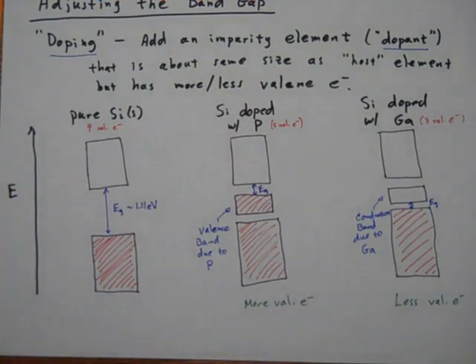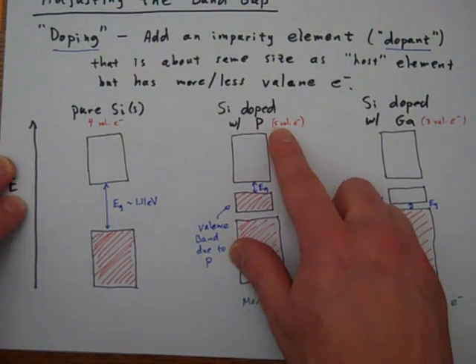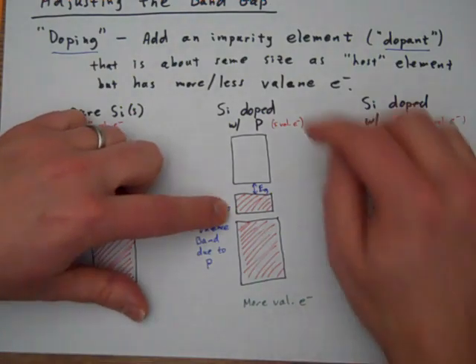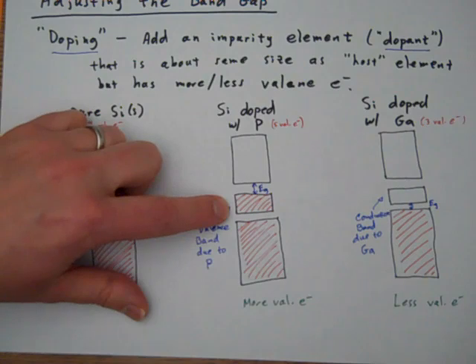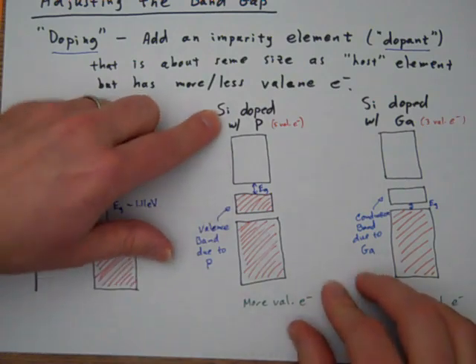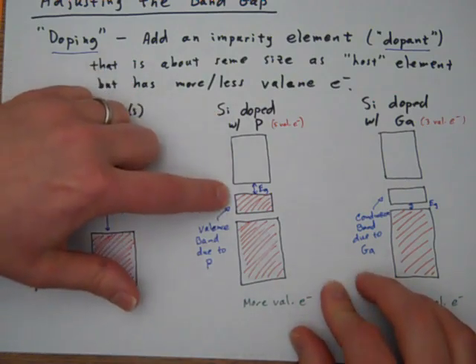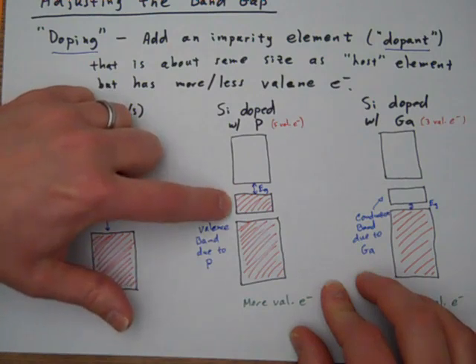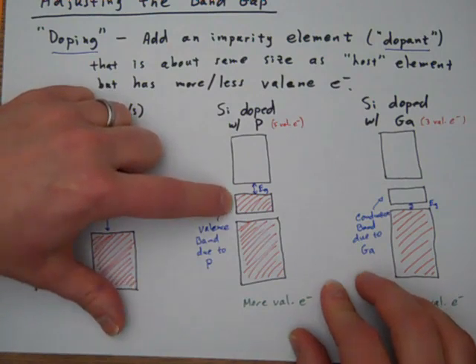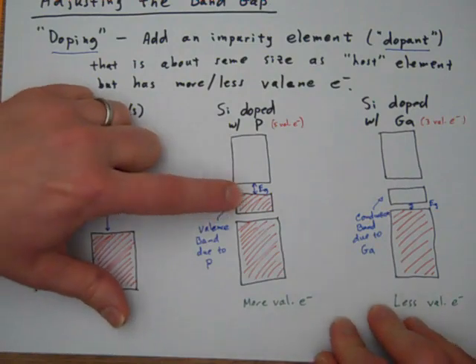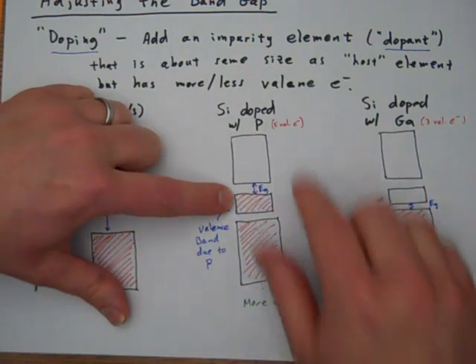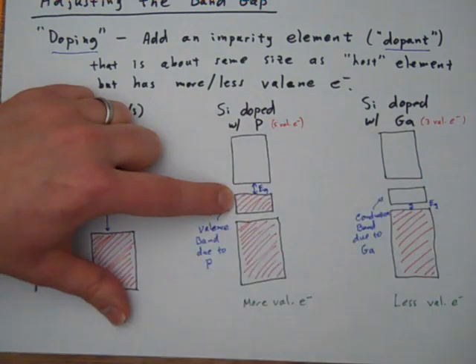So now we've inserted this phosphorus. It's about the same size as a silicon atom. And what phosphorus has is five valence electrons. So those extra valence electrons have to go somewhere. And it turns out that the orbitals in phosphorus are a little bit different than the orbitals in silicon. And what happens is we create a new little band of orbitals, molecular orbitals right here, due to the electrons from phosphorus, due to those phosphorus atomic orbitals that we've put into the mix now.